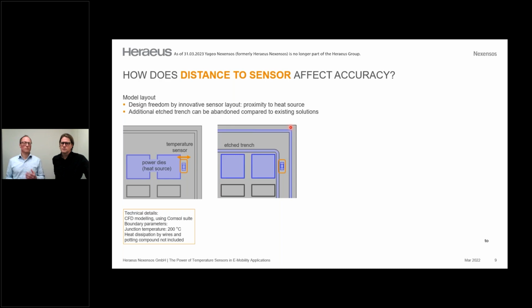Higher operating temperature requires more accurate temperature monitoring. One factor which we would highlight here is the distance, that is what Martin mentioned already, the distance between the temperature sensor and the heat source. In the case of power modules, it's the power die. We started to look at this point to design and develop a temperature sensor starting from a modeling perspective. We looked at a setup where we have the possibility to position the temperature sensor very close to the power die and try to see the difference whether there's an etched trench or not. So we looked at the effects of another technology, which can be abandoned compared to existing technology, brought even closer to the heat source, therefore allowing for faster reaction times and for faster and more accurate temperature detection.